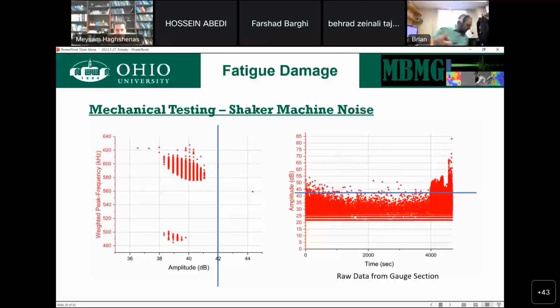So everything up until here was a straight monotonic test, just pulling the material, or doing cyclic loading on an Instron machine or an MTS, low cycles, slow loadings. This is an example of the type of data you get when you do the same procedure on one of those shaker systems I showed you earlier. So when we do that, what we have to realize is these are physical sensors that we're currently using. If we put a physical sensor onto a material and shake the material, we're going to get a response in the sensor that is just the operation of the machinery. It is not any indication of damage.